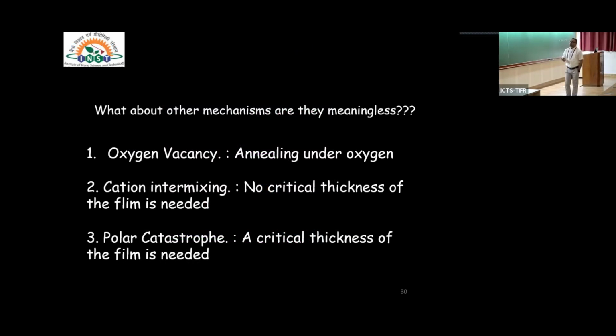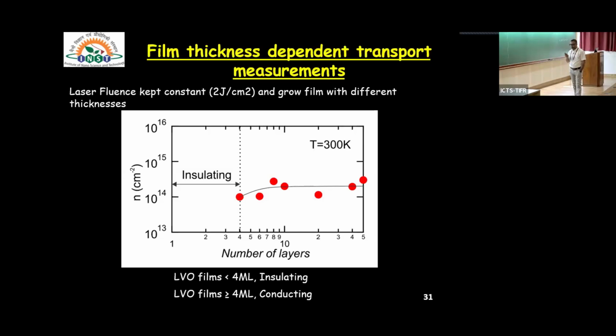So what about the other mechanisms? For example, oxygen vacancy. We have annealed the system and seen there is no change. And for cation intermixing, no critical thickness of the film is needed, whereas for polar catastrophe we need a critical thickness. So what we have done is the following.